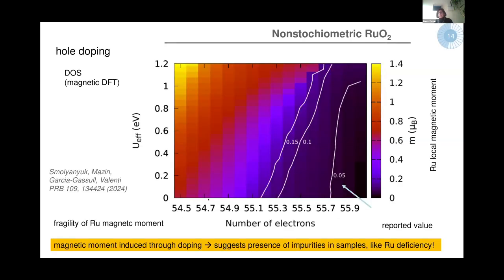So then in fact, what we did is indeed to investigate what happens with the possible appearance of this altermagnetism if we start doping the system. So by changing the number of electrons, what I'm showing here is, in fact, the magnetic moment of ruthenium that is acquired by just doping. This is hole doping the system, as a function of this U effective value. And what you can observe is that as soon as I have hole doping, in the regions of realistic U effective for ruthenium dioxide, we start indeed getting solutions where the ruthenium is magnetic. So doping induces some magnetism in ruthenium.